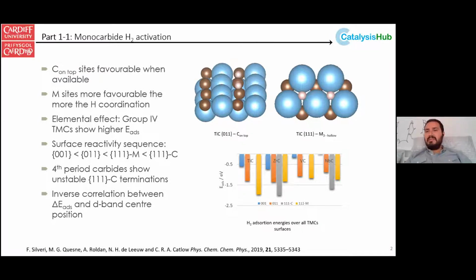Hydrogen, if there is a mixed phase, always prefers to adsorb on top of the carbon sites. We find this with the 011 surface as shown here, and also the 001 surface, which is the dominant phase in any nanoparticle you create from these. The energy, as I'll show you later, for this surface is considerably lower than for the more reactive surface, which in this case is the metal terminated surface. When we have the carbon surface on top, we get a lot of reconstruction. Unfortunately, it's a metastable surface. Although I'll show it in this first slide, we don't consider the carbon terminated 111 plane after this, because whatever adsorbate you have, whether it's water, CO2, or hydrogen, you get major reconstruction on that surface.